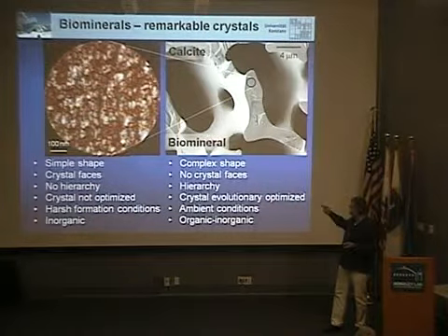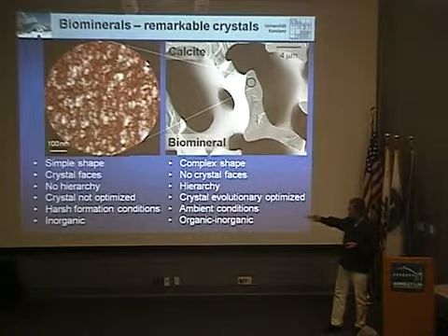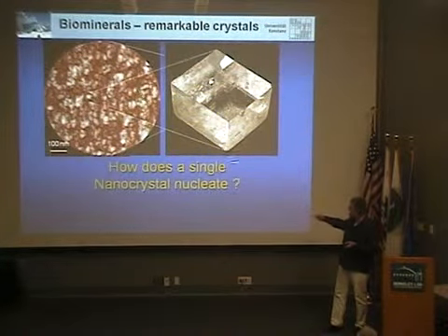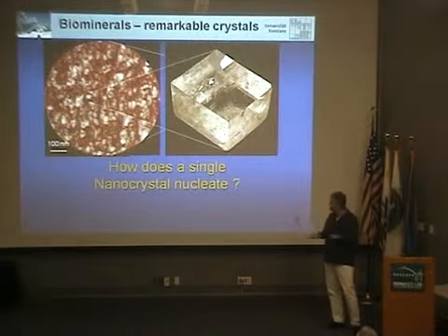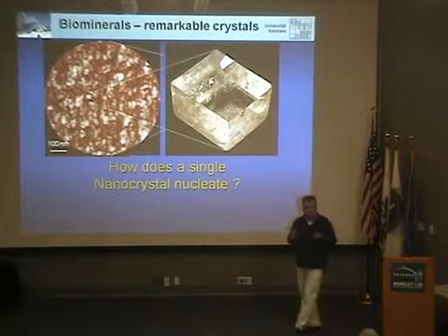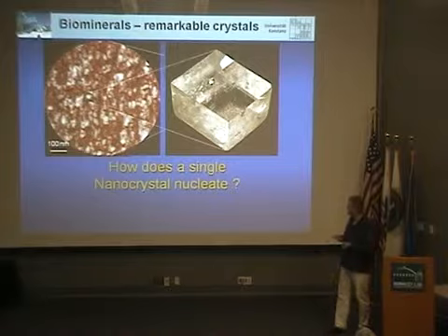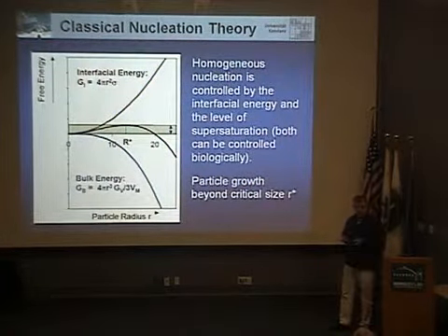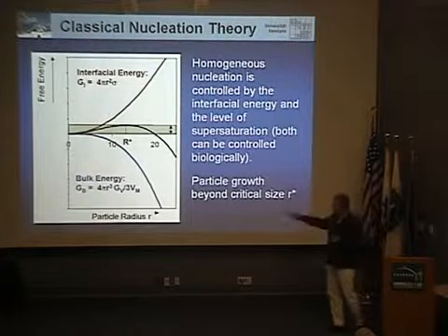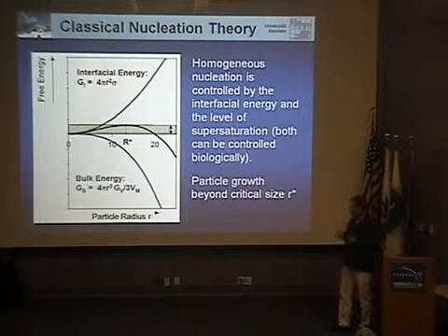And if you now zoom in further, you can see at this cleavage plane that you have nanoparticles, and then the big question is, how do you start to grow this material? And this should start with the very basic question, how does a single crystal nucleate? So if you ask yourself that question, then you can go to the textbooks and come across the classical nucleation theory, and this is basically shown here in the sketch, where you make up a nucleus by investing surface energy.